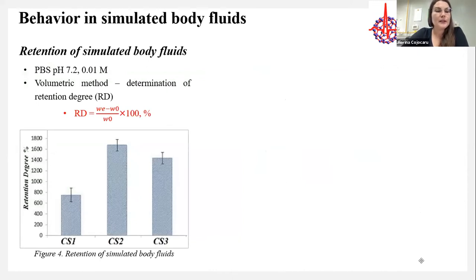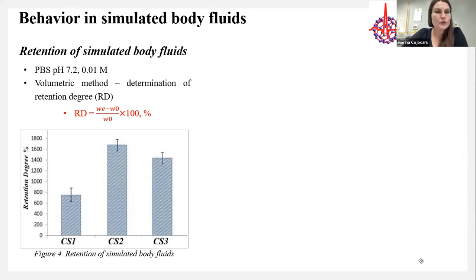The retention of body fluids is very important for bone tissue engineering scaffolds. In our study, we used a volumetric method to determine the retention degree. As shown in Figure 4, we obtained values higher than 600% for the three composite scaffolds. These values can be attributed to the hydrophilicity of the polymers and, very importantly, to the porosity of the scaffolds previously confirmed by SEM.